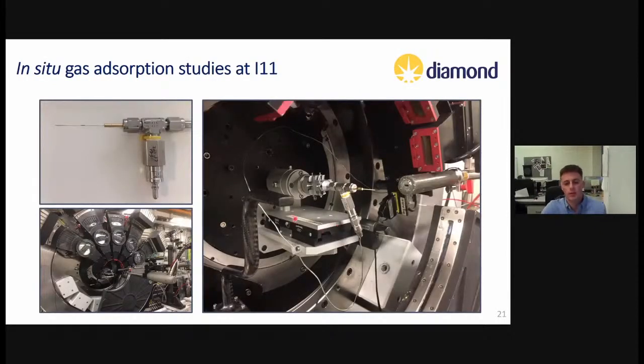So to understand the structural responses to these framework materials under positive pressure of gas, we take our samples to Diamond Light Source, and we use a couple of the beamlines. Initially we used I11, which is the high resolution powder diffraction beamline.